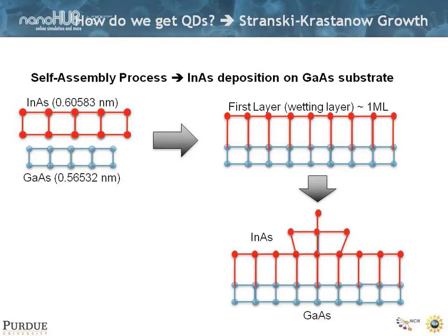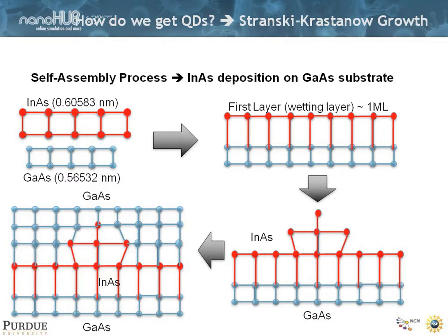Now if you overgrow this with gallium arsenide, which again fits nicely roughly on the substrate lattice constant, you can kind of see that there's a highly strained system and the indium arsenide will push laterally against the gallium arsenide because it would like to expand a little bit. It likes to gain some relief from this pressure so it can do that and it also expands vertically.